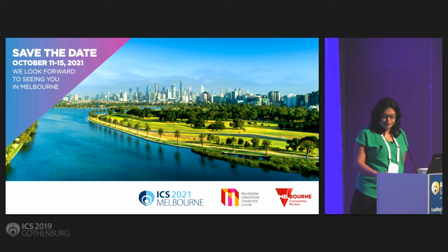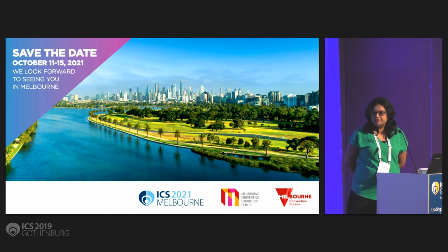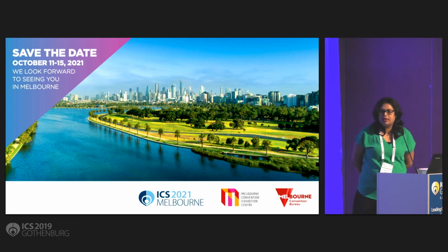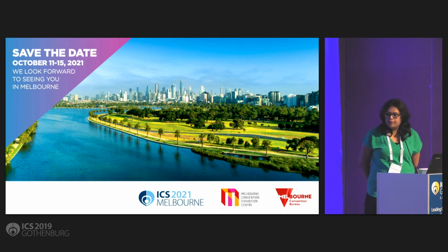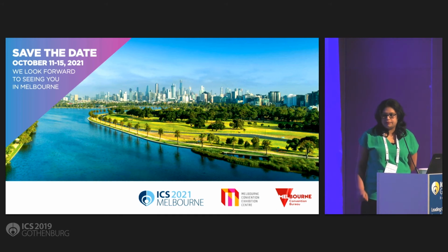I think it's very good that you also looked at porosity, which really led to the improvement of the polypropylene devices. And one of the strengths of the PVDF mesh, in comparison to the polypropylene, is that it keeps its porosity also under strain. So have you compared your porosity size, also under stress, with your new tissue? Do you gain the same porosity?